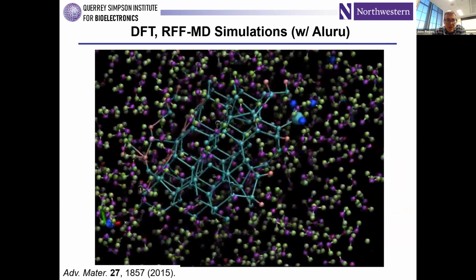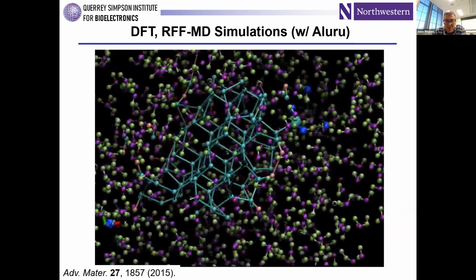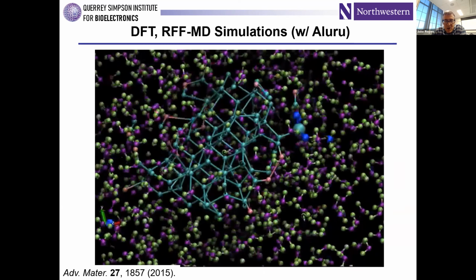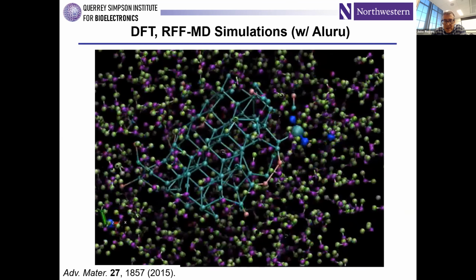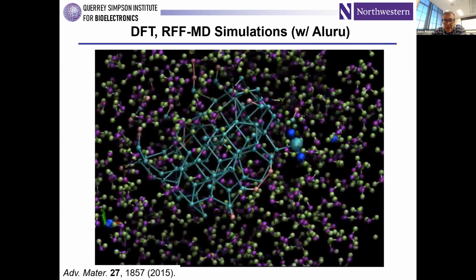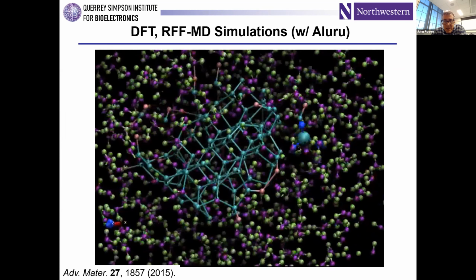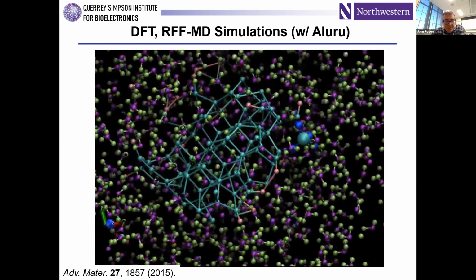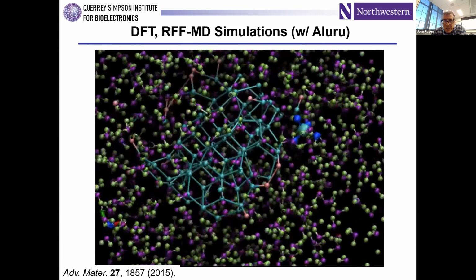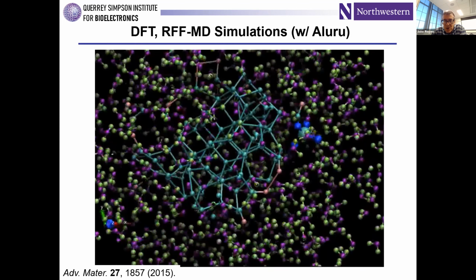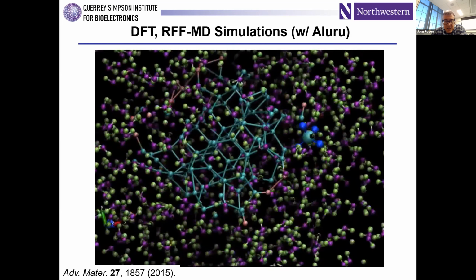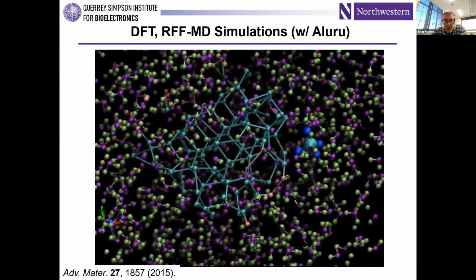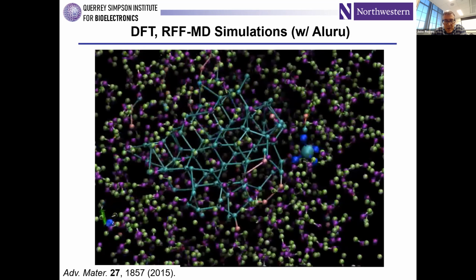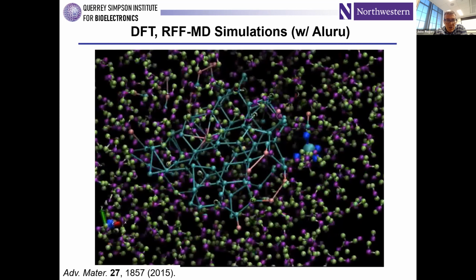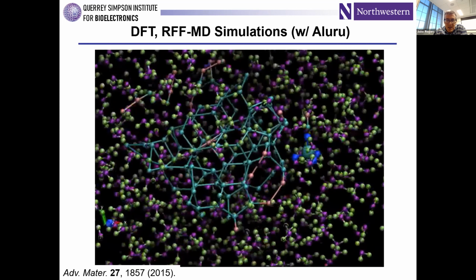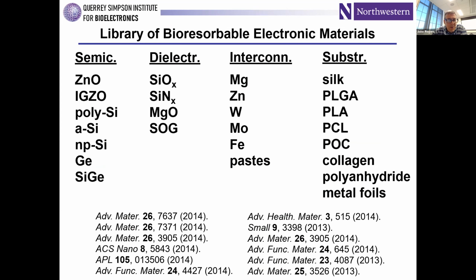And so we spent some time studying the basic material science associated with that. These are MD simulations that were done by a collaborator of ours back at University of Illinois. It shows the dissolution of silicon; that tagged larger silicon atom on the right side of this view graph is dissolving into silicic acid, which is water soluble. You can imagine if you continue this simulation for a long enough time period, that nanocrystal of silicon will be completely consumed by that kind of hydrolysis reaction. So that turned out to be pretty cool, and we got pretty excited.